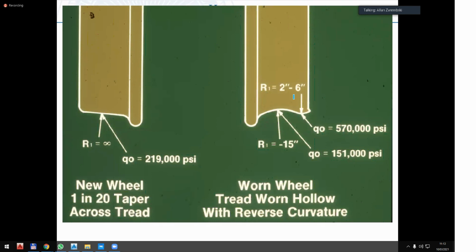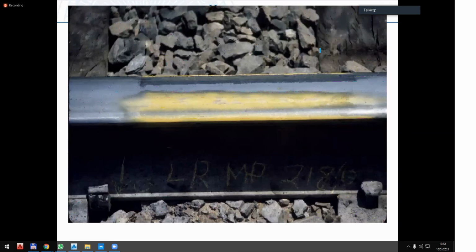Now, the third contact case we have is what happens when the wheel wears. And when a wheel wears, it wears like this. So with a normal wheel, we have good contact. We want to have contact in the center. But as the wheel wears off the center, we start having contact on the outside. You can see here this worn wheel. Here, I'm still running in the center. But let's say I go around the curve. Let's say my curve is forcing me out in that direction. I can start moving this point over here and I start getting contact.